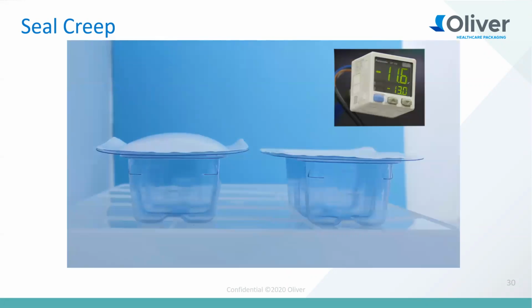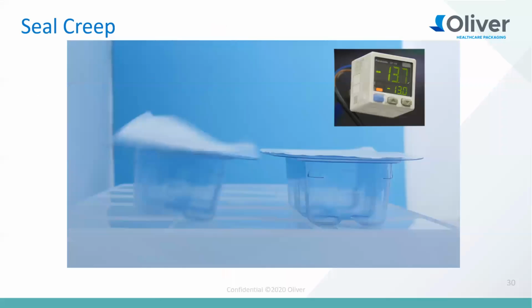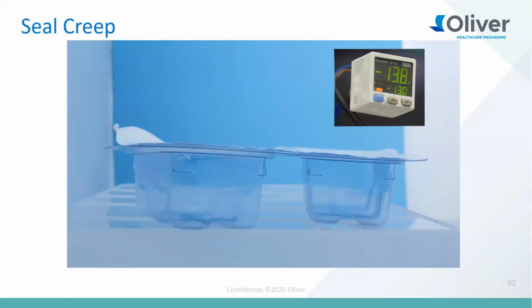In this video, we're simulating what may happen in an environment with changing pressure. This could be in an EO sterilization chamber or a high altitude shipment. In the package on the left, we have covered the porosity. This is a Tyvek lid, but we've covered the porosity with a label that's blocking all the breathability. The one on the right has full breathability, and you can see the one on the left start to inflate. In your EO sterilization cycle or a high altitude shipment, this is a common thing that can happen. The air inside the package wants to escape, and if you're blocking the porosity, it could blow through your seal and cause a complete rupture. Now, this doesn't always mean it's going to happen fully. This is what we call seal creep.